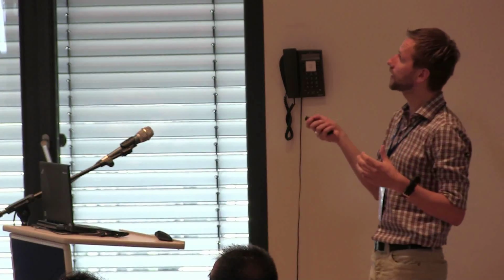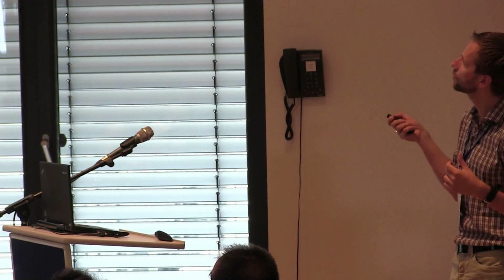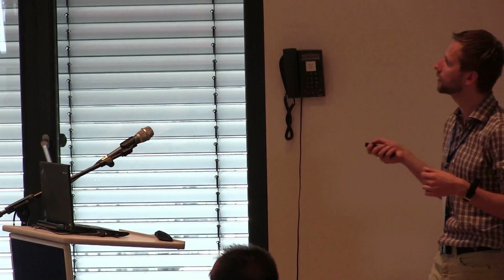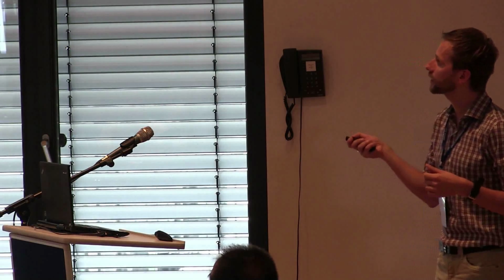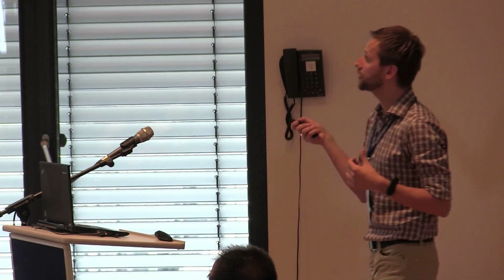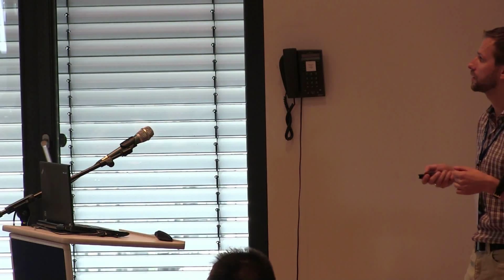The electron gas will thermalize, the energy will equipartition, so the energy will again be shared by all electrons within the gas. You see now they all move a little faster, those arrows are a little longer than before. And this extra kinetic energy simply added to the electron heat. So the only thing that happened in the long run is that the temperature of this electron gas increased due to the new supplied energy, which was kinetic energy of this extra electron. Now it's just extra electron heat that we brought to the system.